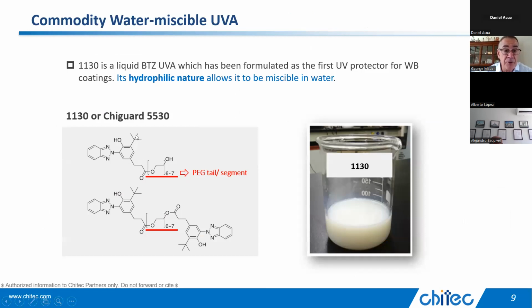This is the 1130 molecule, that old one. Originally, Ciba-Geigy came up with it back in the 80s. ChiGuard makes it. We sell a version also, 5530. And for those of you that are using it, I don't want to say it doesn't work at all. It just isn't a high performance, long-term UV absorber because it does go away. This segment in here, which is 6 to 7 units of ether, these are ethylene oxides that have been extended off of the benzotriazole. That's susceptible to oxidation and cleavage. And we think that's one of the reasons why the 5530 or the 1130 isn't performing well when you go out into the, say, 3 to 10 year period, especially 5 to 10 years, it's not helping you.